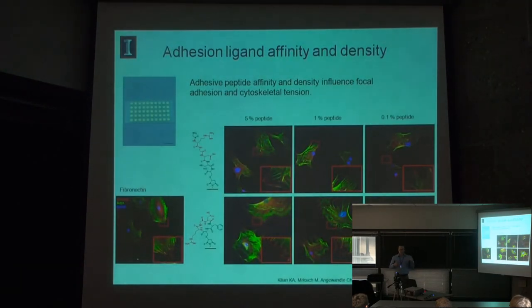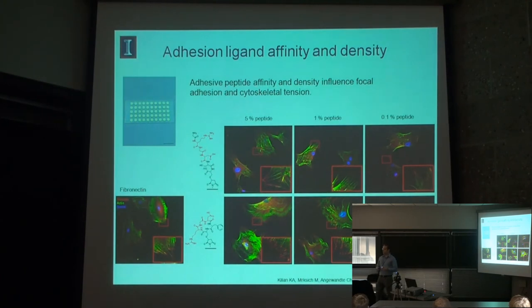And so we thought, if you get more focal adhesions, you get better spreading, maybe we'll get more bone cell differentiation. And so we used an array of gold islands for this, where each one has been modified with different peptides so we can control within the same experiment. And this is the phenotype of these cells on linear peptide, where you see they're well spread, they've got lots of focal adhesions on the side. But when they're on the cyclic peptide or on fibronectin, which has a loop domain where the RGD is, so it's already in that bent shape, right? We see lots of focal adhesions, many more than the linear case, and in particular on the interior of the cell. And they tend to be larger in area, have more cytoskeletal tension, etc.